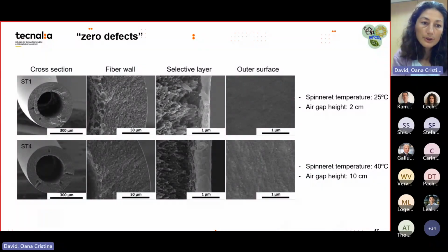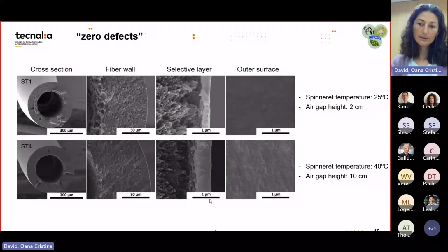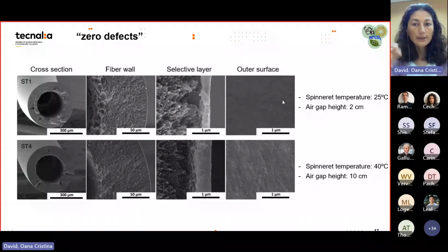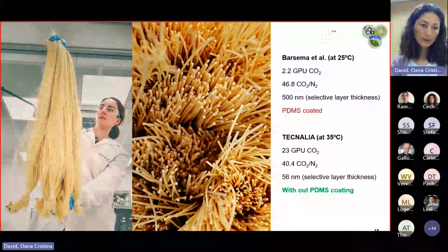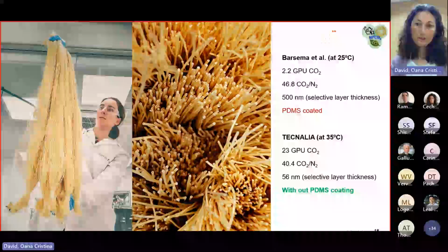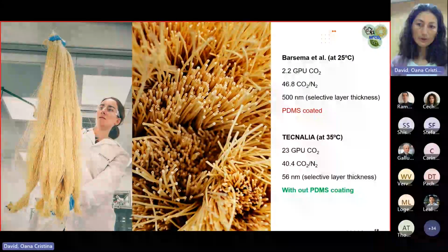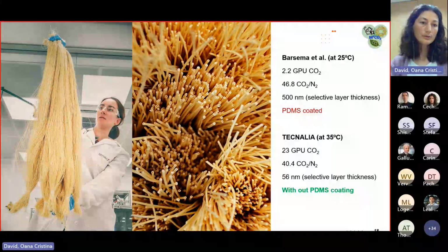So here are a few images of the fibers of the two examples at these two very different air gaps, 2 and 10 centimeters. And also by this representation, it's observed that the selective layer at 2 centimeters is thinner than at 10 centimeters. The first image is the entire cross section, then the fiber wall, then the selective layer, and the last image is the outer surface. Here also on the outer surface, the surface is neater, so there are fewer defects at the lower air gap. And we also scaled up this fiber production, and we achieved very good results without performing any PDMS coating.